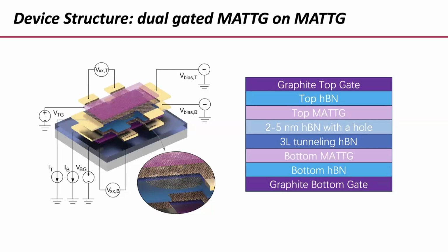And then we have a thicker hBN where, everywhere except for one region, there is a hole. In that region, here the contrast is a little bit bad with the light, but in that circular region a micron in diameter, there is a hole. So the top and the bottom magic angle tri-layer graphene are connected by this tunnel barrier, but in the electrode regions, they're separated by this thicker hBN. It's a little bit complicated, but I hope most of you are following the structure.